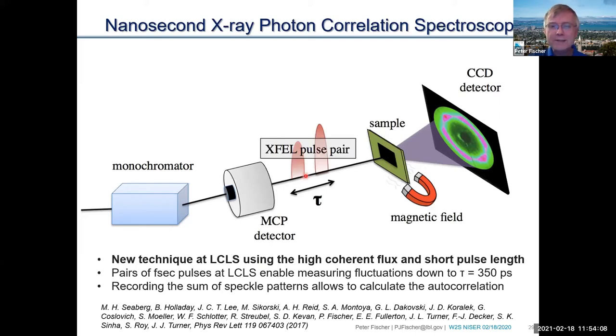That means you freeze in the first diffraction pattern, the timestamp when it's in one fluctuation, and then shortly after that you hit it again, and then you encode basically this kind of multiplexed signal into the CCD detector. And of course, what you have to do, and this is the work by Matt Seaberg, a student, is basically deal with these autocorrelations and deconvolute the signals there. Anyway, he looked into speckle patterns and calculated autocorrelation.